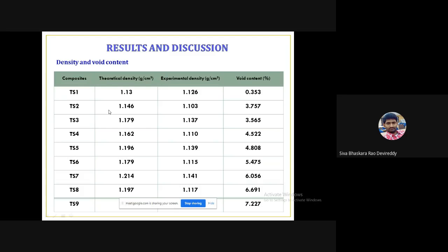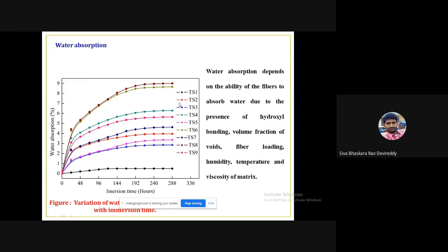Coming to the results and discussion, theoretical density and experimental density are shown in this table. The difference between these two gives the volume of the void content. If you observe, by increasing the fiber content, the void content of these composites increases. Water absorption of the composites also increases with respect to immersion time. The maximum water absorption was observed for the composite TS8, which is broom grass root 28% without any glass fiber.